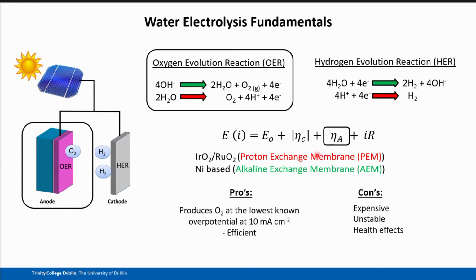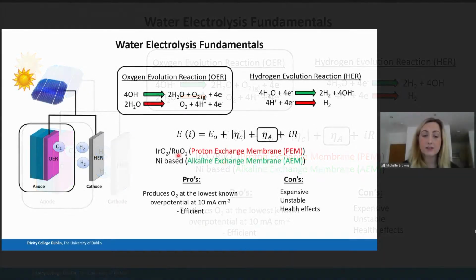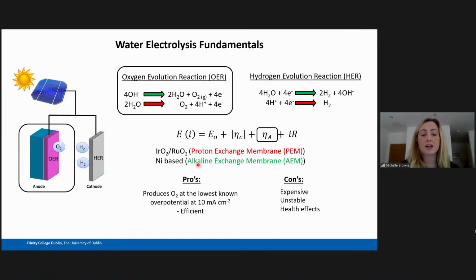So for proton exchange membrane state-of-the-art materials, these materials are very expensive, and they're also quite unstable at operating conditions. And then for the alkaline exchange membrane state-of-the-art materials, they have a lot of adverse health effects. So nickel complexes and nickel-based materials are actually carcinogenic. And then also, when you compare the alkaline state-of-the-art materials to the proton exchange membrane materials, they are significantly worse at producing oxygen when compared to the acidic-based ones.